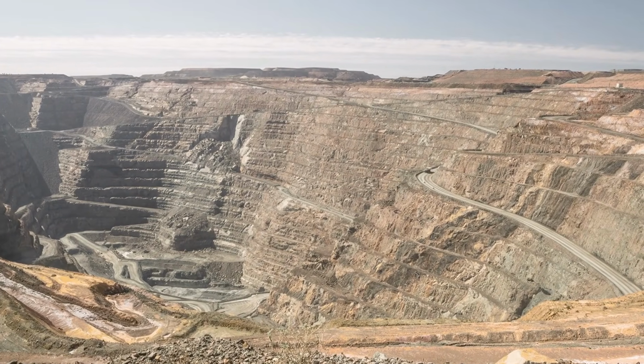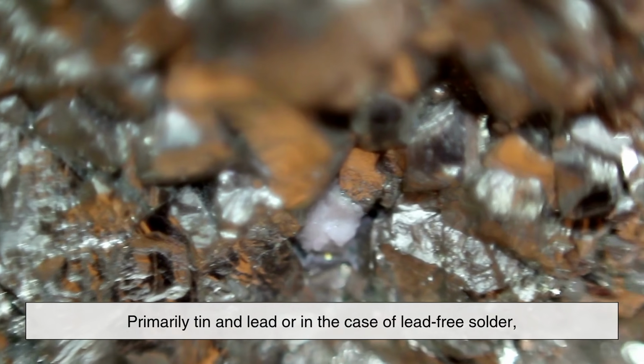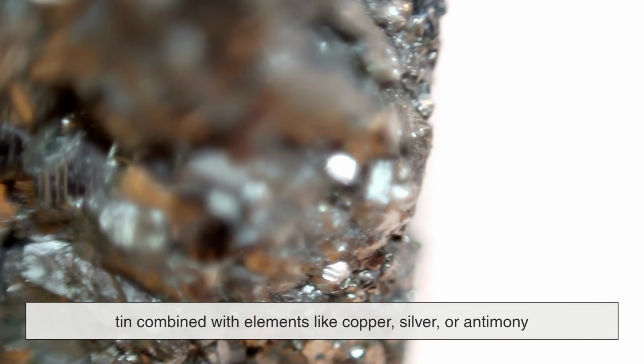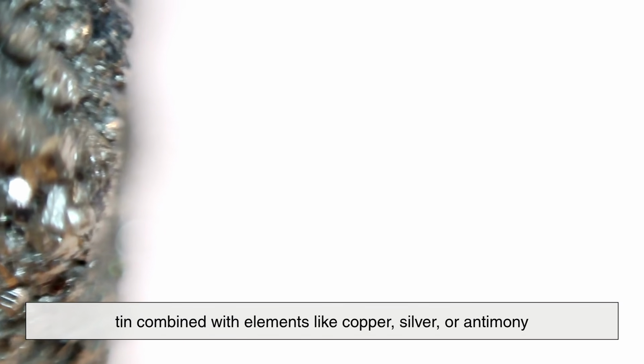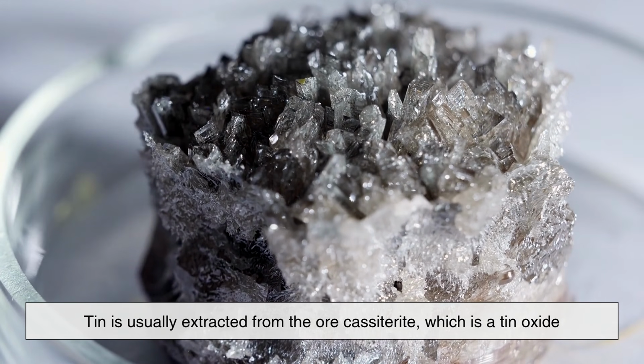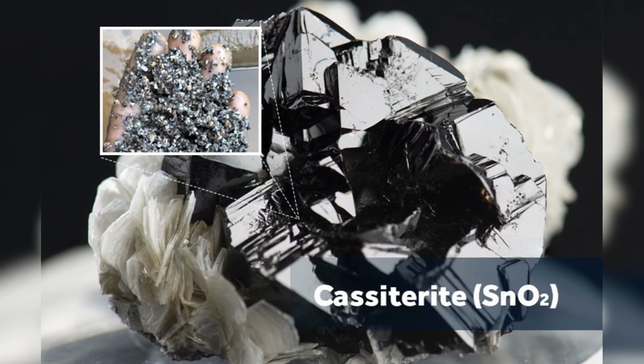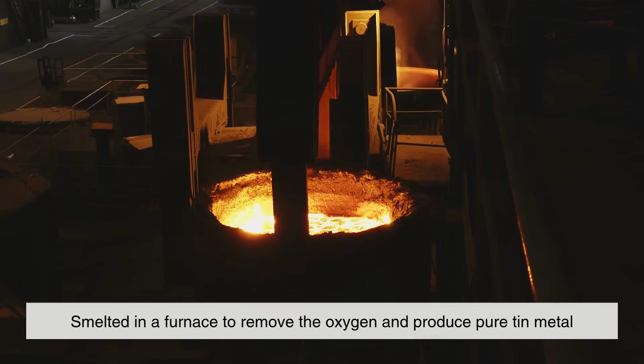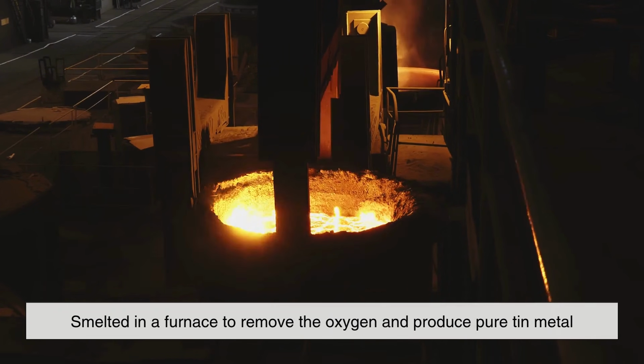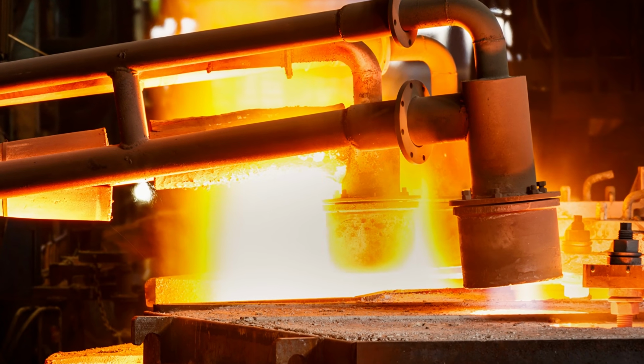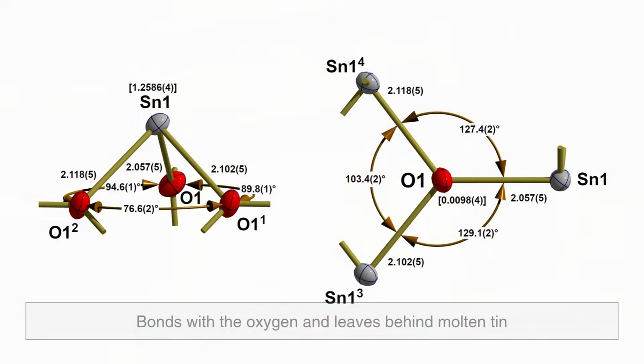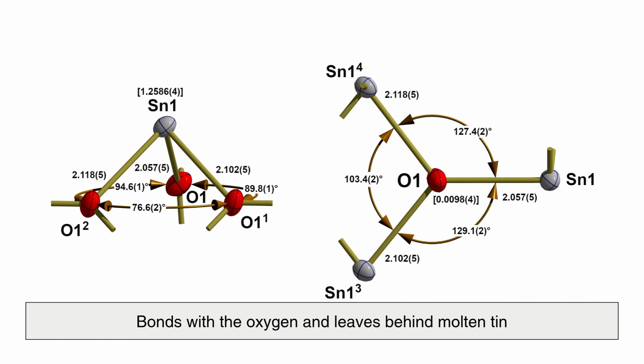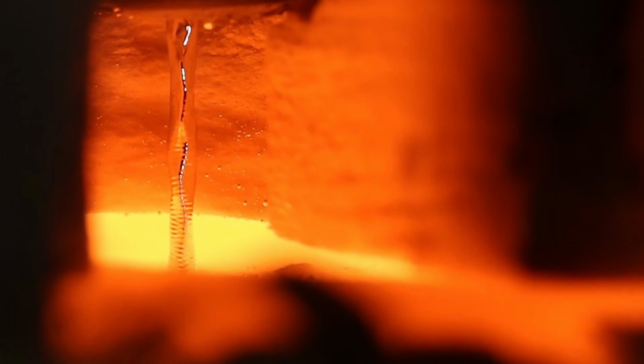So, how does solder go from raw ore to that shiny spool you pick up at the hardware store? The process begins with the mining and refining of metals, primarily tin and lead, or in the case of lead-free solder, tin combined with elements like copper, silver, or antimony. Tin is usually extracted from the ore cassiterite, which is a tin oxide. This ore is crushed, concentrated, and then smelted in a furnace to remove the oxygen and produce pure tin metal. The process involves heating the ore to high temperatures in the presence of carbon, which bonds with the oxygen and leaves behind molten tin. This molten tin is then poured into molds, cooled, and later shipped off for further processing.